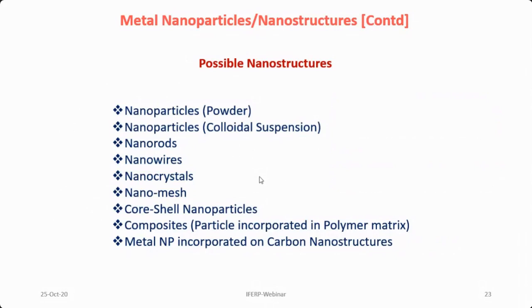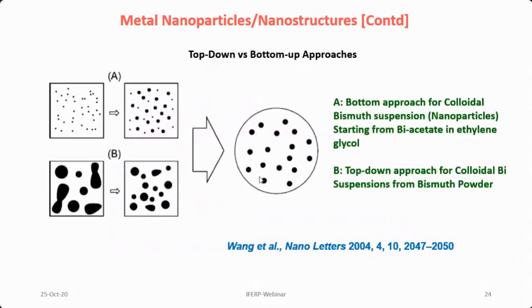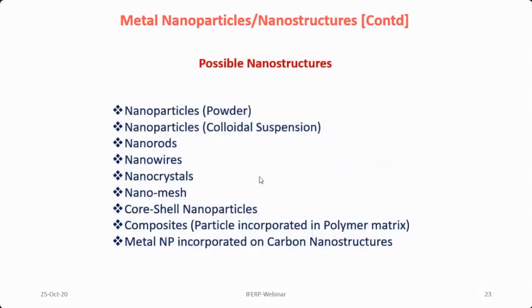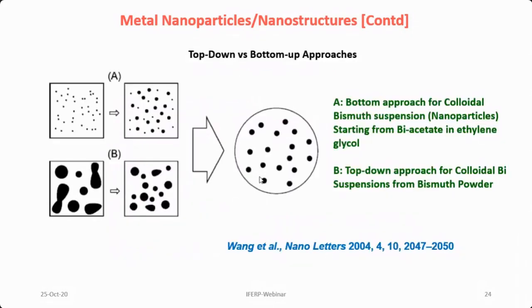But when it is put into a proper technique, in imaging technique, you can actually see what is there. And then there are other techniques also which are not imaging, but still they will tell what type of material is there, whether it is rod, wire, mesh, or particle. Normally people think everything is nanoparticle and they get dissolved into solutions. They don't get dissolved. If you dissolve it, then it becomes a kind of molecular solution. Like suppose I am putting silver in nitric acid, then the silver nanoparticle will get dissolved, but it will become silver nitrate again. Then it is no use. So those type of misconceptions need not be there.